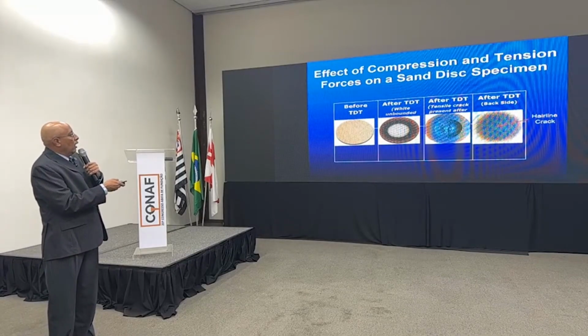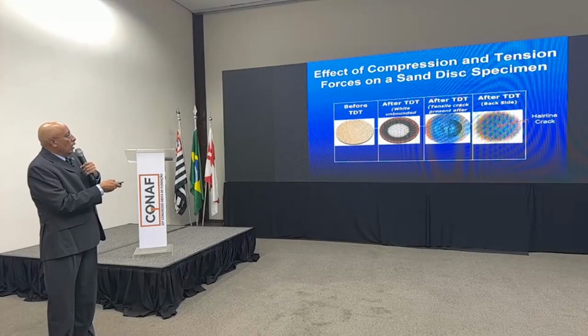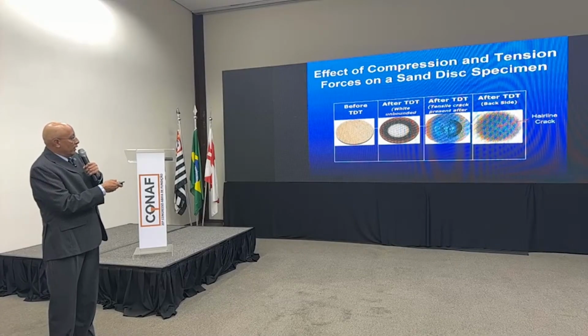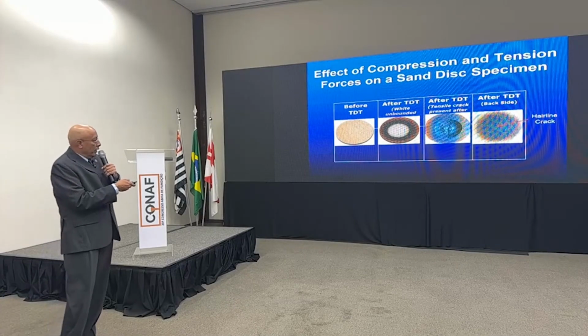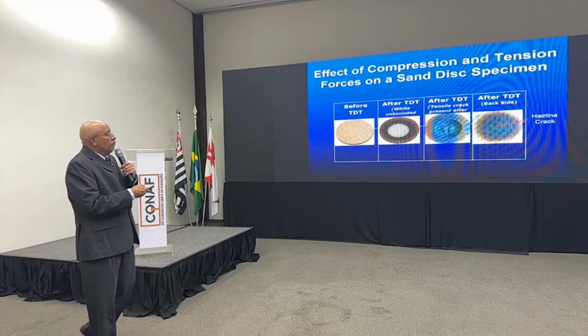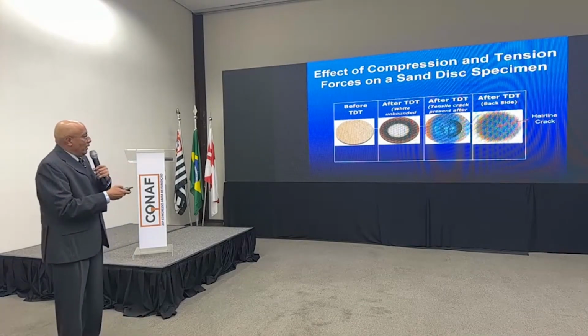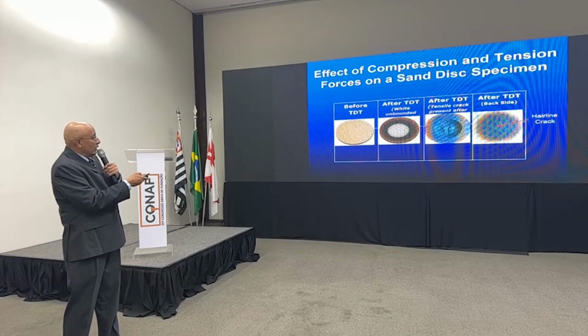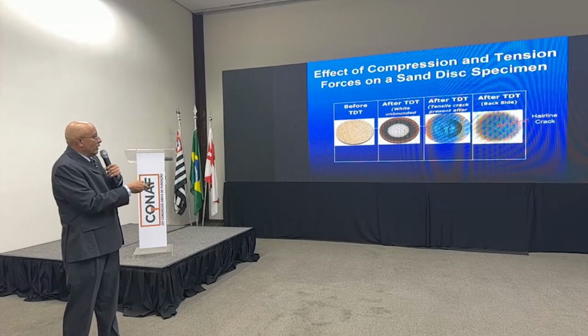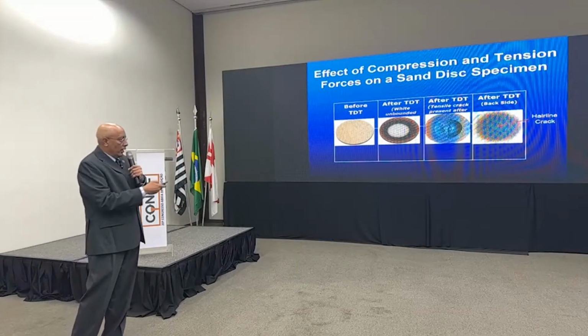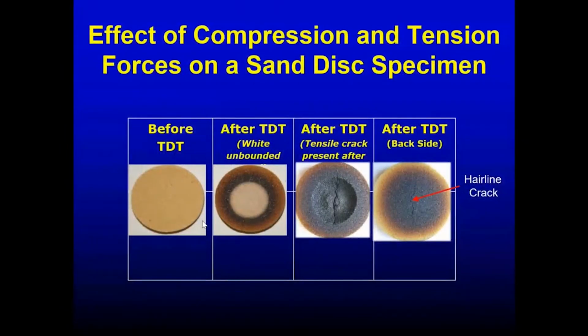This is the heat affected zone, the HAZ, where you literally are burning out the binder systems. When that binder system is blown away, you could see where at one time there would be a vein or crack in the system, and that hairline crack on the backside. That we could indicate, and we know when that's happening. How do we know when that's happening?